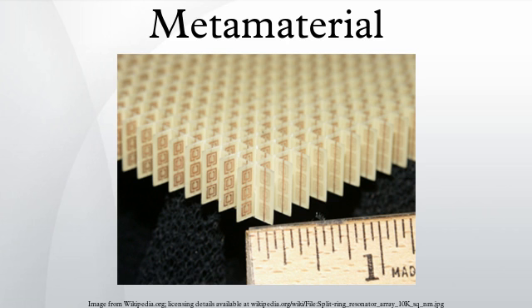Wave propagation properties in chiral metamaterials demonstrate that negative refraction can be realized in metamaterials with a strong chirality and positive ε and μ. This is because the refractive index has distinct values for left and right, given by. It can be seen that a negative index will occur for one polarization if κ is greater than the square root of ε_r μ_r. In this case, it is not necessary that either or both ε_r and μ_r be negative for backward wave propagation. FSS-based frequency-selective surface-based metamaterials block signals in one waveband and pass those at another waveband.